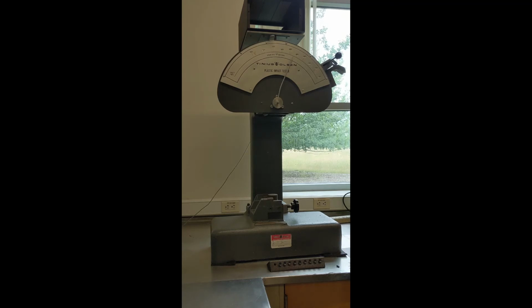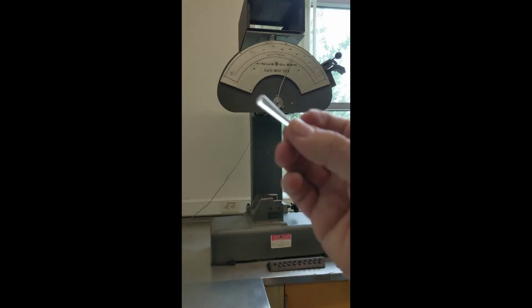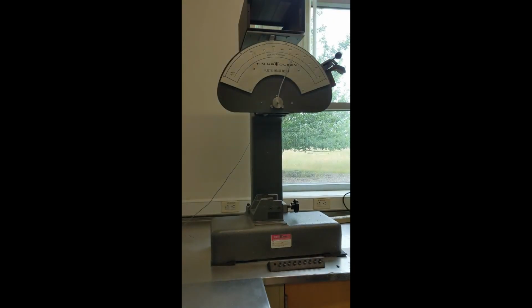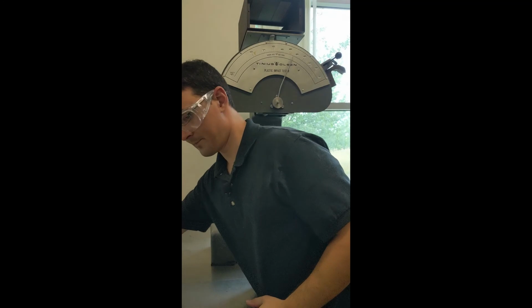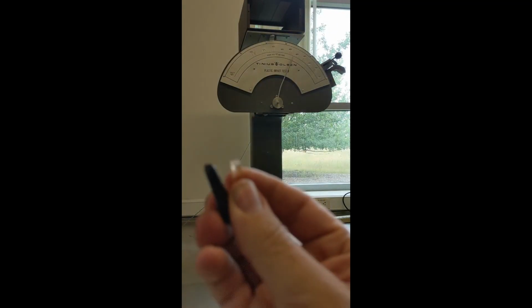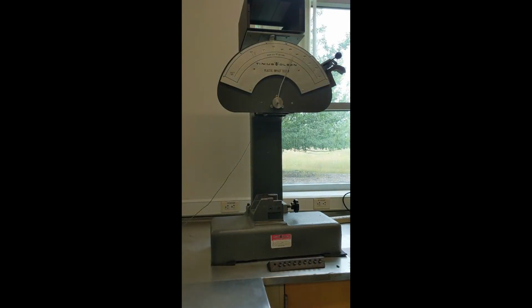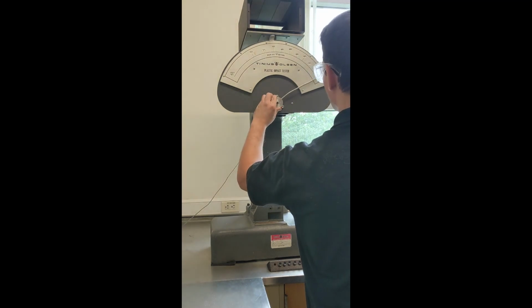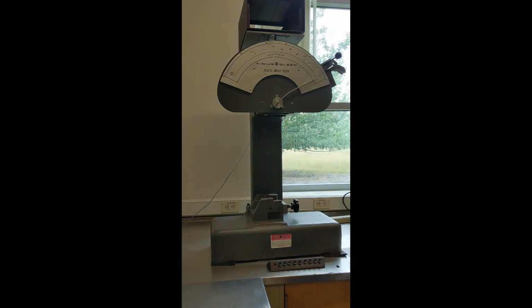Now by contrast, I have here a piece of a golf tee of a different polymer. This one should have a slightly different impact strength. And what I want you to do is observe the break as well as the sound that it makes when it breaks. So first of all, that was a much higher pitch break. And also, when we look at that break, it is much more brittle. You can see that this clear specimen was much more brittle, had a much lower impact strength. In fact, that one registered down here almost at 0, possibly the smallest amount that the impact tester could record.